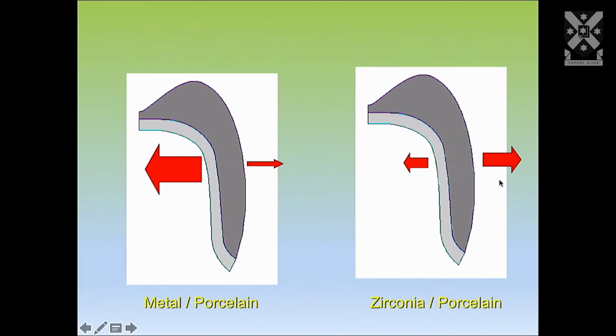And the implication of this is that when the crown comes out of the furnace, it's losing the heat, in the case of a metal, from the inside to the outside. So as it's contracting and cooling, it goes from a liquid, because the porcelain has to be fired and enameled, to a solid. It's solidifying from the inside out. But in the case of the zirconia, it's losing heat equally, both from the outside and the inside.